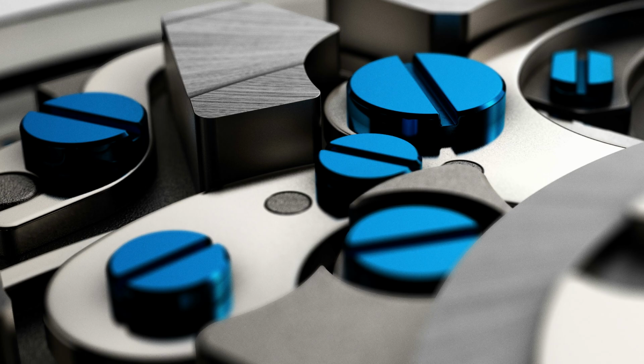But it's actually a kind of coincidence that the ideal temperature to temper a watch screw is also the temperature that gives that beautiful dark blue color. And also there is a second reason, but this is debatable: this blue passivation layer actually creates a kind of film that protects the material from oxidation or rust.